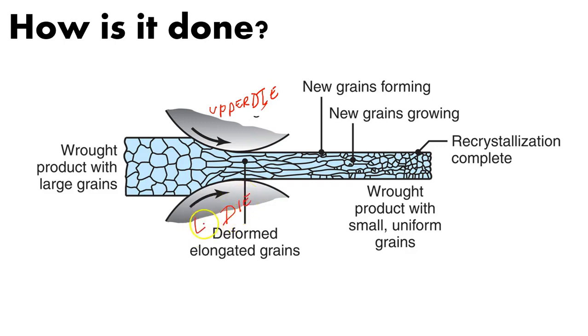So we just say lower die. So an upper die and a lower die that are coming together in that beating process, that compressive process. What you can see here is that you're actually beating the metal down. You're actually changing the shape, and you're therefore changing the size of the crystals as it comes out of that die process.